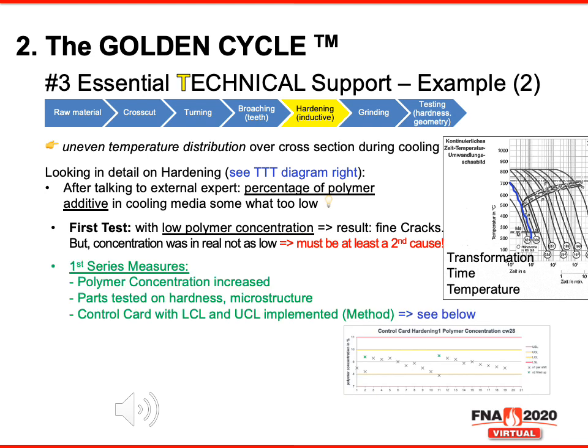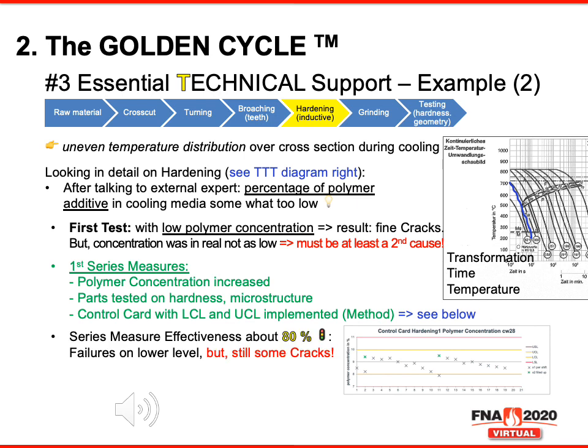The series measures we started now, that was first the increase of polymer concentration. The parts were tested on hardness, microstructure, etc. And we established a control chart with a lower and upper control limit for the polymer concentration. You see it below. And the series measure effectiveness, I talked about this before. It's very important to measure it and to always implement only one measure. The failures were really on a lower level. The measure effectiveness was about 80%. That means yellow traffic sign, but there were still some cracks.